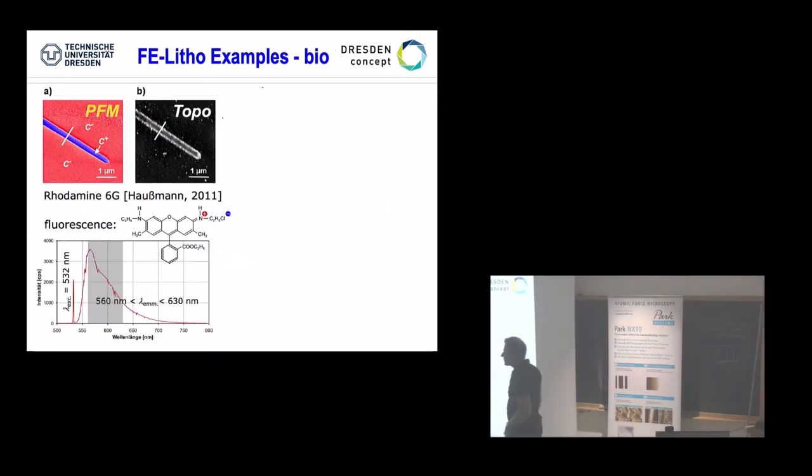And that's exactly something we have been playing with a lot, saying, okay, why not take materials, and this is just rhodamine 6G, which is just a dye. So you're using this basically for staining. In early times it was also used for lasers. You mix it into a liquid and make a so-called dye laser at this wavelength. You see nicely it's 560 nanometers, tunable over 70 nanometers. So we deposit this exactly along the domain wall rim, and hence we can have a trapping of these molecules only at that wall.